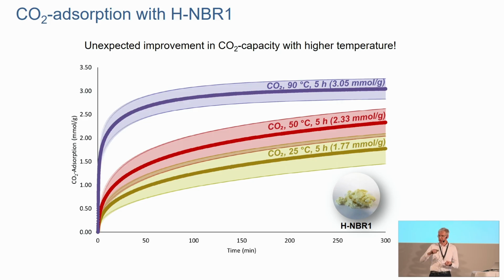And that was unexpected because we would expect the reverse, that the capture should be better at lower temperatures because you need heating to release the CO2. And yet we were getting better values at higher temperatures.